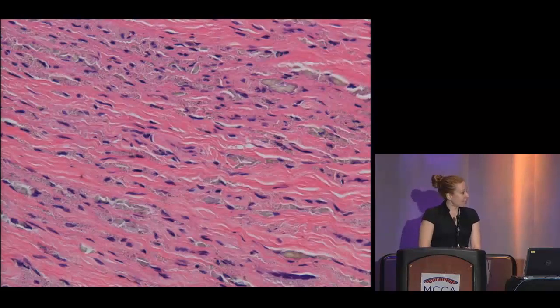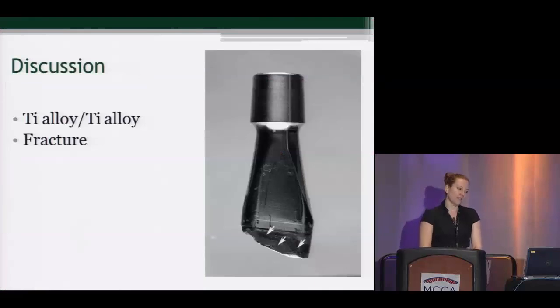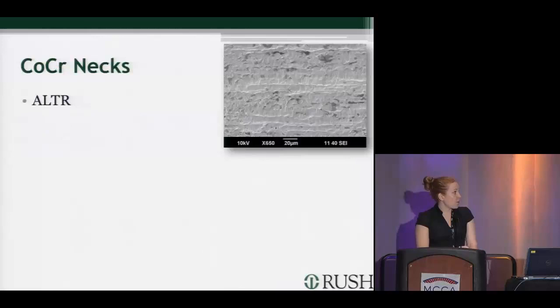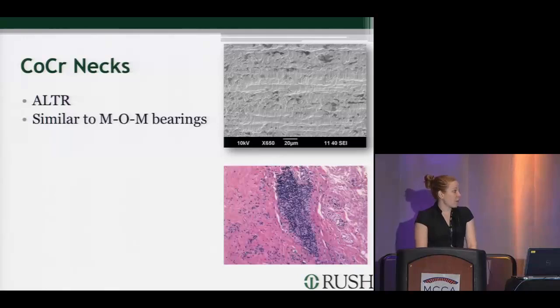Here in the periprosthetic tissues, we can see these cobalt chromium corrosion products within macrophages. So titanium alloy necks have often resulted in the fracture of the modular necks. The main issue with cobalt chrome modular necks seems to be an adverse local tissue response, which is similar to what we see in metal-on-metal bearings.